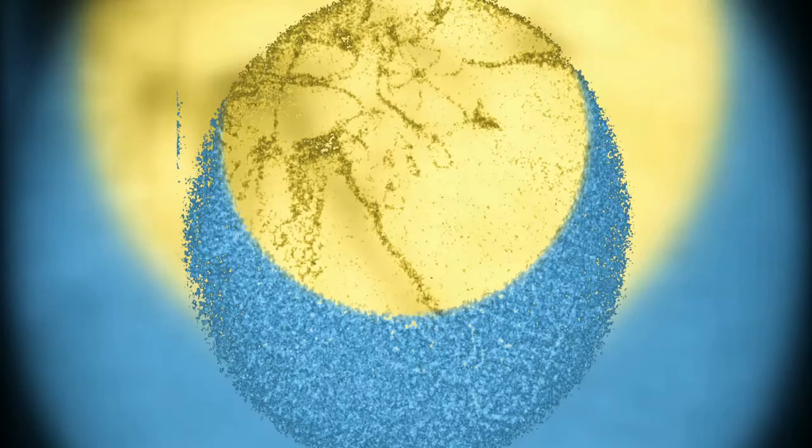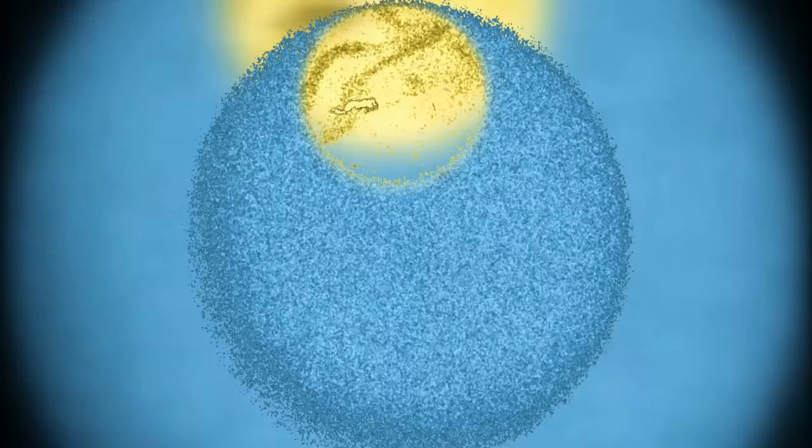What that lets us see is the fundamental processes that are actually happening in nanotechnology. So in these kinds of phase change memories, we can watch individual nucleation and growth events of single crystals form and expand in an amorphous material.